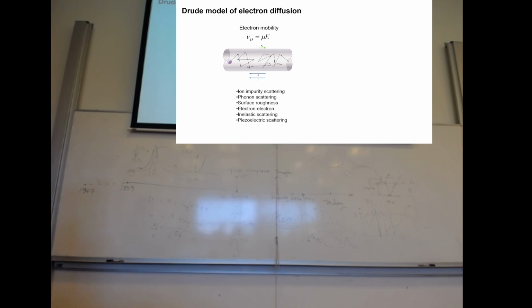In graphene it's the same case here, except that all the conditions are now two-dimensional. So we have to reduce the impurities, for example, encapsulate graphene somewhere. Also, we have to make the surface flatter. Why? Because any kind of fluctuation in the z dimension will scatter your electrons. Or the tension, defects, or even long-distance Coulomb scattering, will degrade your graphene quality in terms of electron mobility.